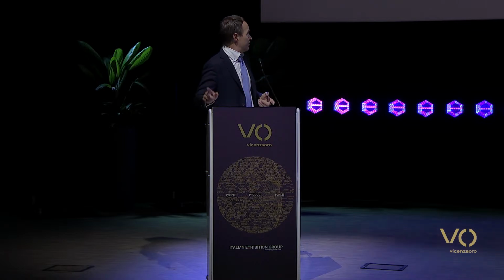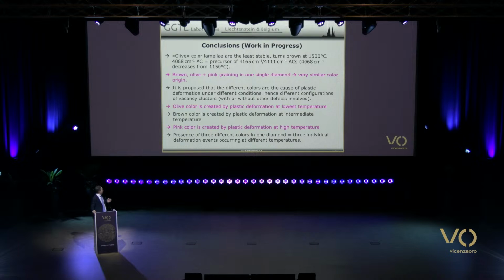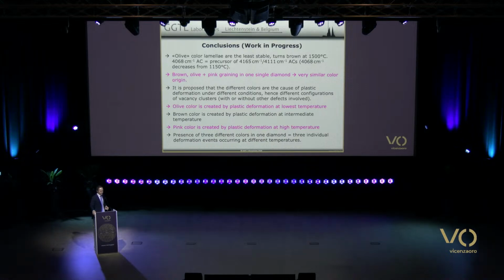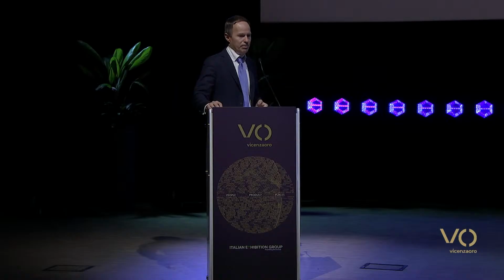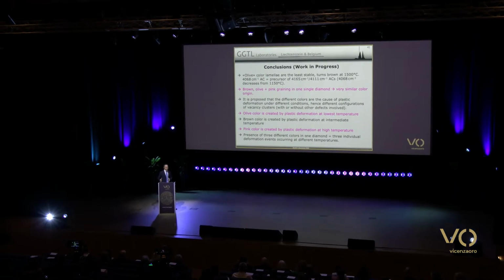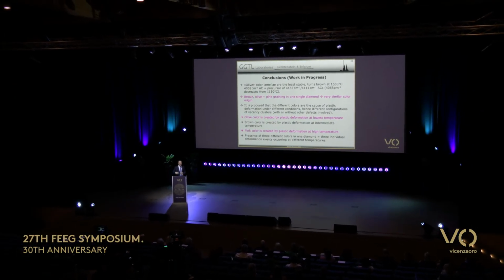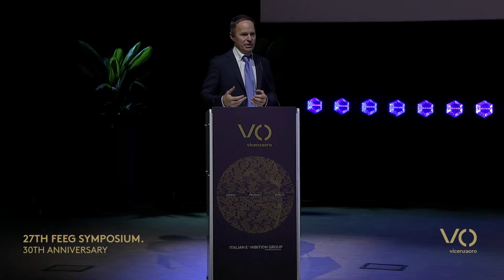We're suggesting that the olive color is created by plastic deformation at the lowest temperature, brown color by plastic deformation at an intermediate temperature, and pink color by plastic deformation at the highest temperature. This explains why we don't have type 1b diamonds in pink: their deformation happens at such high temperature that all the single nitrogen would be aggregated. So it's impossible to have type 1b in pink, at least naturally colored.